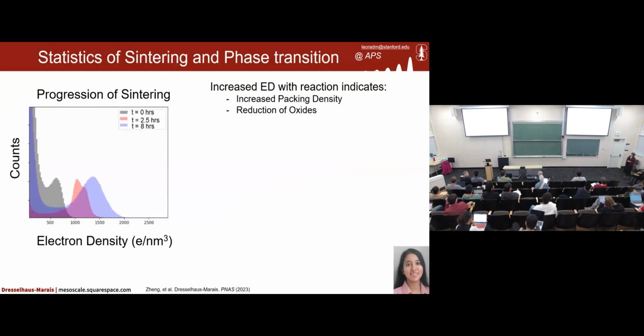So Shubetsha and my group then went a step further and did an imaging experiment called X-ray ptychographic tomography, which effectively is a way of giving us a view that can go down to 30 nanometers in resolution, but can also resolve based on electron density, i.e. it can give us information about whether we are in a metallic state or an oxide state at any little spot within our material.